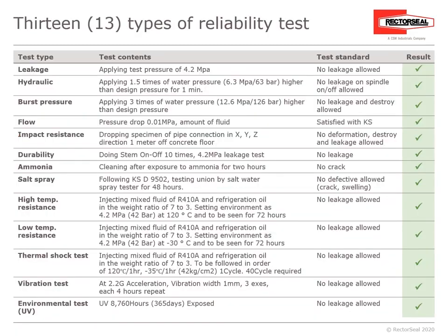Here we see the 13 different types of reliability tests. Test type of leakage, applying test pressure at 4.2 MPa. Test standard, no leakage. Result, no leakage. Same thing for hydraulic, applying 1.5 times of water pressure higher than the design pressure for 1 minute. There's a burst pressure test, applying 3 times of water pressure.